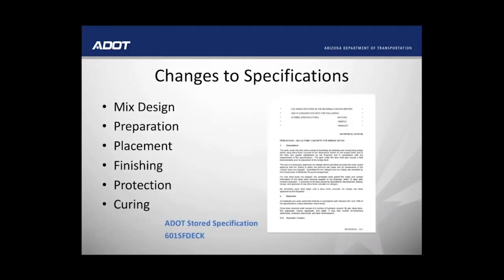So to help facilitate placement of the silica fume concrete, we developed 601 SF deck, which is an ADOT stored specification, and we included a few different requirements in it, in addition to what we talked about with the mix design. For preparation, we talk about a field demonstration to make sure all of the equipment and materials are coordinated. For placement, we try to limit the placement to within 10 feet of the screed. We try to limit hand tooling for finishing the concrete. And we also talked about windscreens and fogging equipment to try to reduce evaporation. For curing, we extended the length of the curing from 7 days to 10 days for the water cure. In general, all of these requirements are not so much related to the materials themselves, but to the quality of the construction and the workmanship.